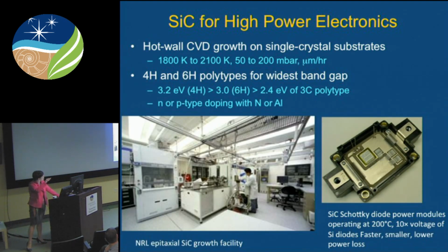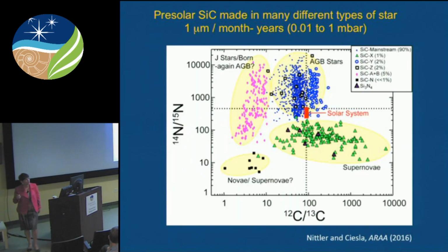In the pre-solar world, you make silicon carbide not in those CVD chambers, but in a variety of different stars. Let me just point out that the pressure range you use in the lab is something like 50 to 200 millibar, which gets you about a micron or so per hour of growth rates. In the stars, you're working at several orders of magnitude lower pressures, and you get a micron in months to years.